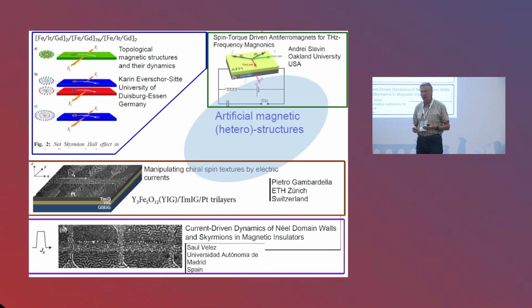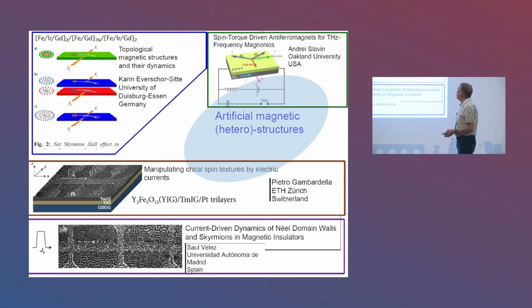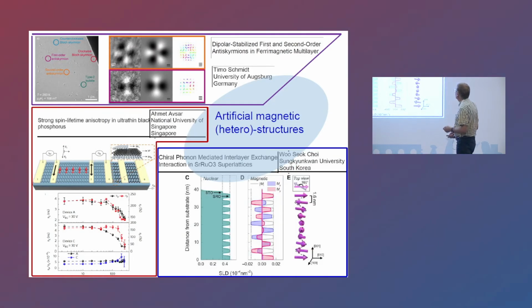So actually, at present, generation of terahertz radiation, in particular monochromatic radiation, is a big problem. And this concept suggests making a bilayer structure of a conductor, so this is a platinum conductor, and a conventional antiferromagnet, nickel oxide. And so by running the current through platinum, one generates a spin torque, which generates monochromatic terahertz radiation in this antiferromagnet. Next, there was also one contribution about the stabilization not only of the skyrmions, but also the antipodes, so to say, antiparticles, so antiskyrmions, given by Timo Schmidt from the University of Augsburg.